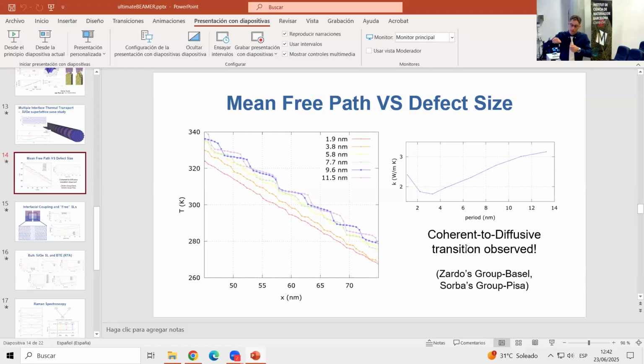If you can go at lower and lower temperature, you would see that the minimum shifts as well, because phonons would become able to experience a superlattice made of bricks, basically. Whereas if you take bricks and you do like this, you don't see any coherent regimes just because you have primitive cells this large. So I would say that for these reasons, the fact that you observe a minima doesn't really have to do with the number of phonon modes that you have, but rather with the fact that you have a scale.